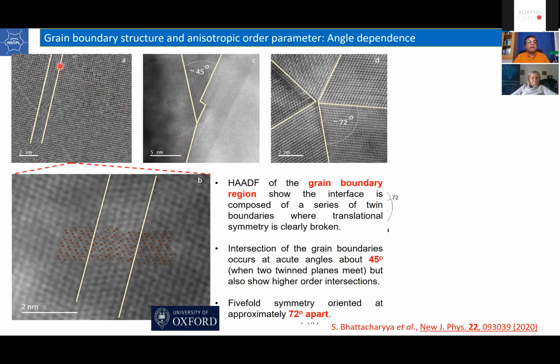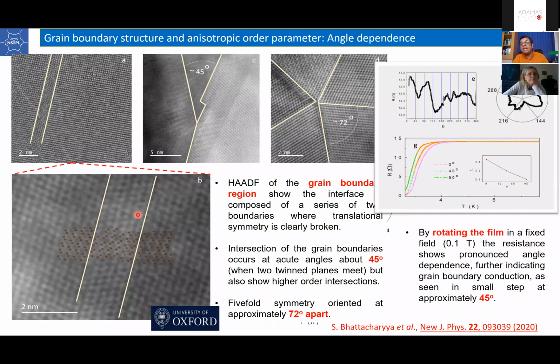So what you see, the grain boundaries, I think this is the best quality picture of nanodiamond we have ever seen. And you can see the twins, this kind of angle, 45 degree. This is the microstructure which can be compared with the electrical transport. Namely, when you rotate the sample as a function of magnetic field, you can see a periodicity which is nearly 45 degree. So it matches with the microstructure of the sample. So we can say this microstructure is very important for the transport property of the material.